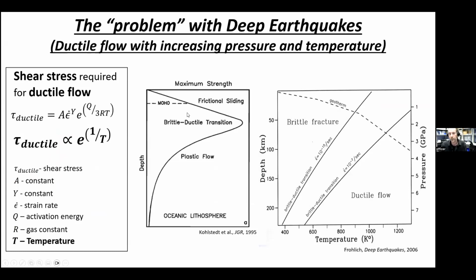So if you look at the strength of rocks as a function of depth, they get stronger and stronger and stronger as you're increasing pressure, but eventually you reach this ductile transition, and then they start to lose strength and have ductile flow. And here on the right, it just shows the actual depth. So if we're going down along the geotherm, somewhere between 50 and 70 kilometers, we transition from brittle behavior into ductile behavior. So based on what we know about rock mechanics and rheology, we wouldn't expect earthquakes to occur below about 70